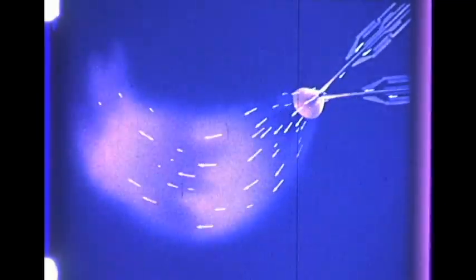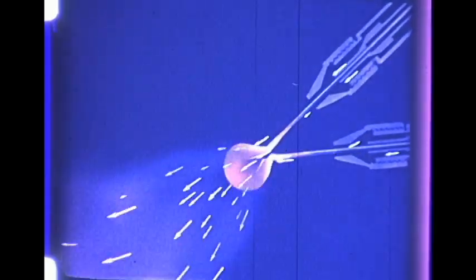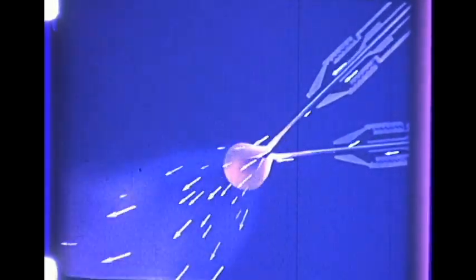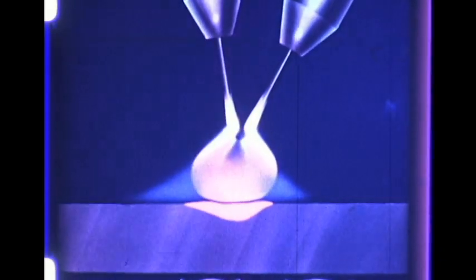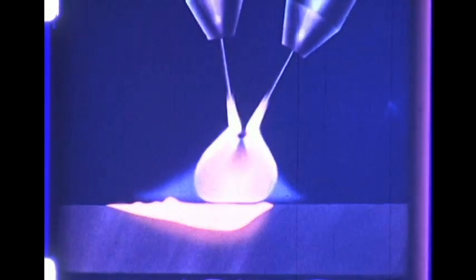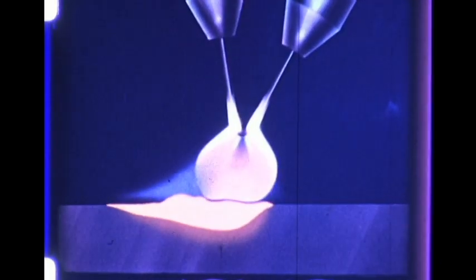The unique feature of this process is the use of a hydrogen flame to surround the arc. Hydrogen gas flows out through the nozzles of the electrode holder, around the electrodes and the arc. The hydrogen flow cools the electrodes and prevents their rapid evaporation. The action of the arc changes the hydrogen into atomic form — hence the name atomic hydrogen. As the atomic hydrogen contacts the work, it changes back to its molecular form, and a rapid transfer of heat is obtained.